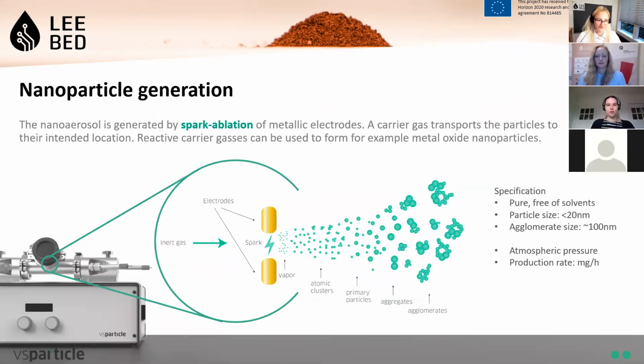So within the generator, you see two electrodes are installed, and the generation of the nanoparticles is based on spark ablation. So between these two electrodes that are installed in the reactor, there's a little gap and a gas flowing through. You apply a voltage to these electrodes, and when the energy is discharged by a spark, the spark heats up the electrodes and evaporates material. And this vapor is then transported along with the gas, is cooled down, and atomic clusters form that will form primary particles. And these primary particles will agglomerate into larger agglomerates.